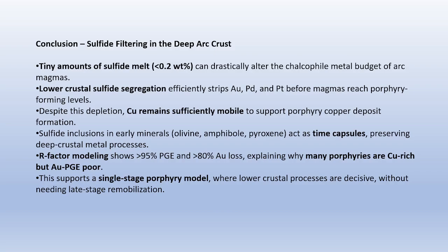And evidence comes from sulfide inclusions preserved in early minerals like olivine, amphibole, and pyroxene. And these inclusions are essentially time capsules, capturing the exact moment when metals were partitioned away in the lower crust. It's a glimpse into processes we rarely get to see so clearly in other magmatic arc settings. And the modeling is equally striking. Our depletion factor calculations show that over 95% of PGEs and more than 80% of gold can be stripped out by deep sulfides.